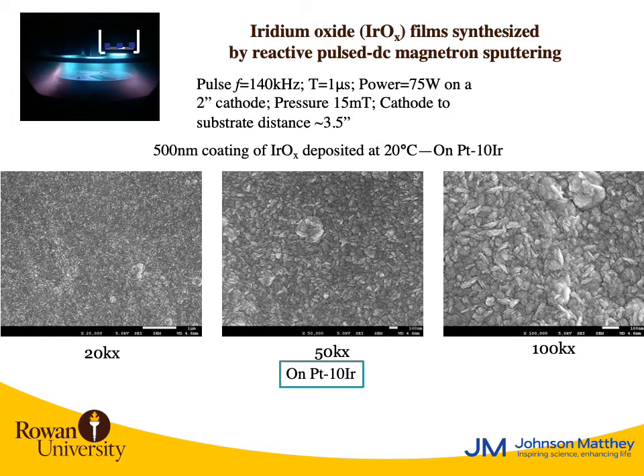This work uses pulsed DC sputtering in a reactive environment in order to make these coatings. So here you see the parameters of the deposition: 140 kilohertz for the frequency, the period, so the off cycle, is 1 microsecond, and the power is 75 watts on a 2-inch cathode. The pressure in the chamber totally is 15 millitorr, and the cathode to substrate distance is about 3.5 inches.